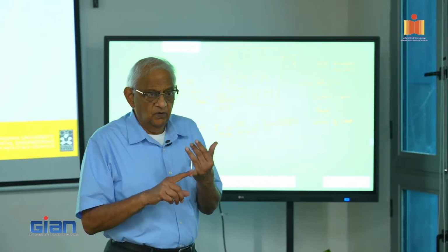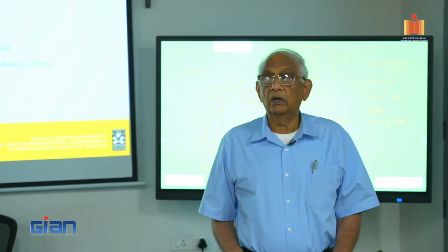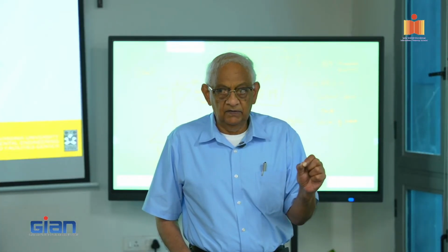That's the first quality check. The second one is the dynamic mechanical thermal analyzer, which also tells you about Tg. The third one is not necessarily the resin, but the resin system, which implies that you are cutting corners by having higher percentages of filler. Okay.